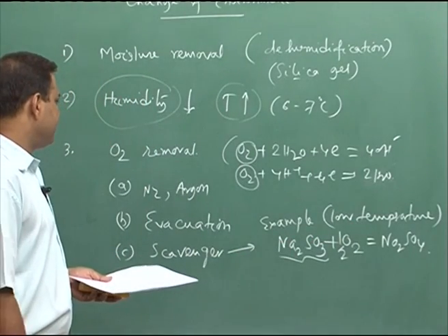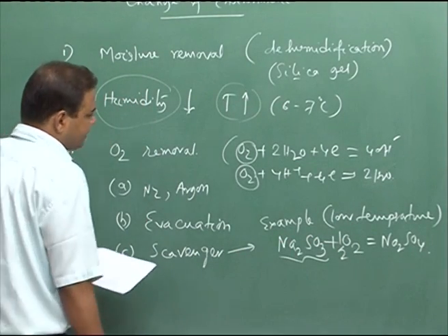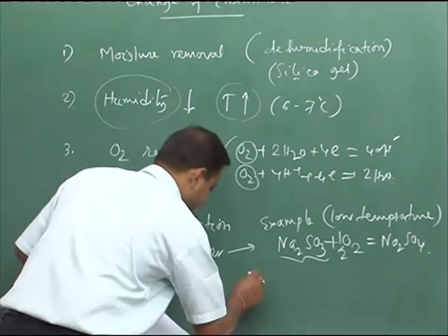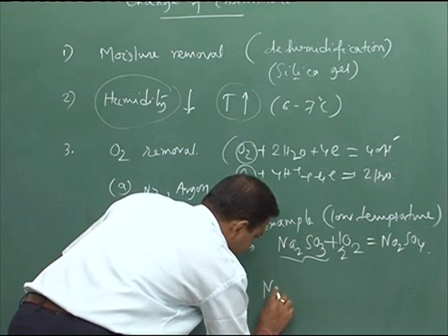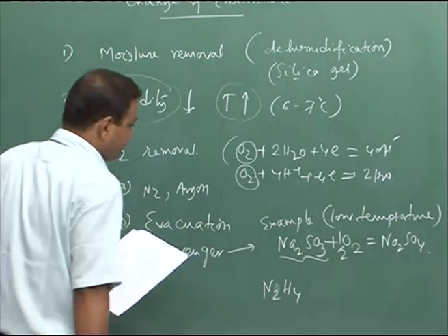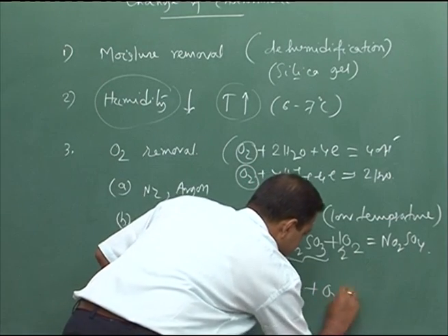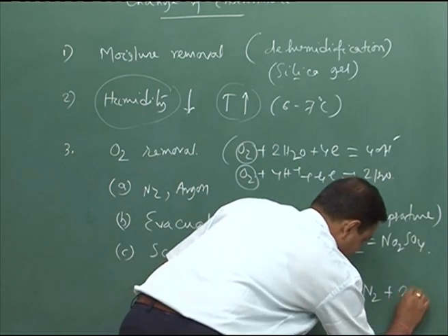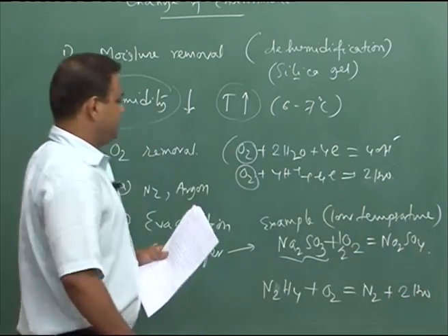Or at high temperature we can add N2H4, hydrazine, which will also react with the dissolved oxygen and form nitrogen gas and water molecule.